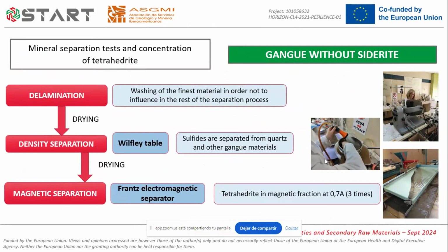And so once we have the samples ground and sieved at the different grain sizes, we move on to the next step. As I have explained, there is a difference in the treatment of the samples depending on the minerals that are present. If we have a gangue without siderite, which is the case of Delfina and Coriayu mines, we have followed 3 steps: first, a delamination, that is the washing of the finest material in order not to influence the rest of the separation process. After drying, we have done a density separation with the Wilfley table, where sulfides are separated from the quartz and other light minerals. And finally, after drying, we have done a magnetic separation with the Frantz electromagnetic separator, where the tetrahedrite is separated in the magnetic fraction.